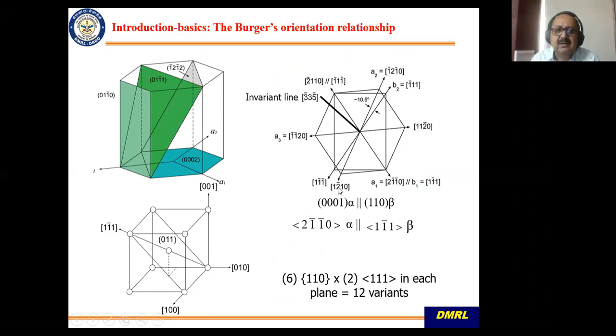Now, I will just try and explain the Burgers orientation relationship. If you have looked at the microstructure of titanium alloys, mostly you must have seen in Ti6Al4V the beta to alpha structure. You see a very geometric pattern, and that is because of this Burgers orientation relationship. Most of the transformations in conventional titanium alloys are beta to alpha or alpha to beta. Now, the close packed plane of this, which is this plane, maps onto this plane, and one of the close packed directions matches perfectly with this, and the others are slightly off.